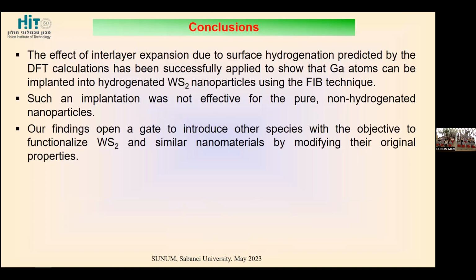I would like to conclude that because of the previous hydrogenation, we now open the gate for functionalization of these nanoparticles, also for electronic applications. We can implant gallium and other species at not so extreme conditions and then achieve much better electronic properties. We already did some electrical conductivity measurements, which proved that these nanoparticles have better electrical conductivity, less resistivity, less surface resistivity, and so can be applied in a lot of devices which otherwise require much better electronic properties than pure nanoparticles.